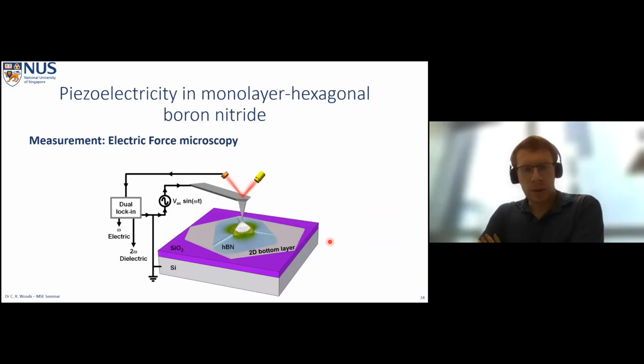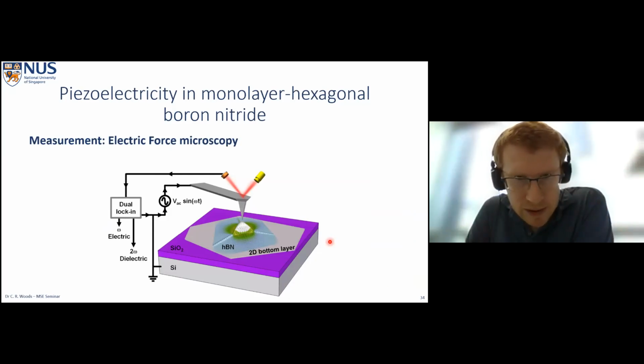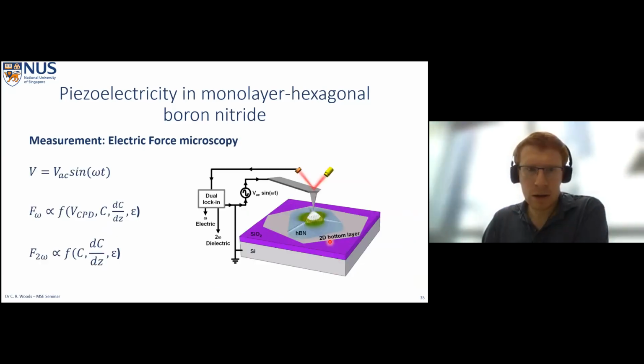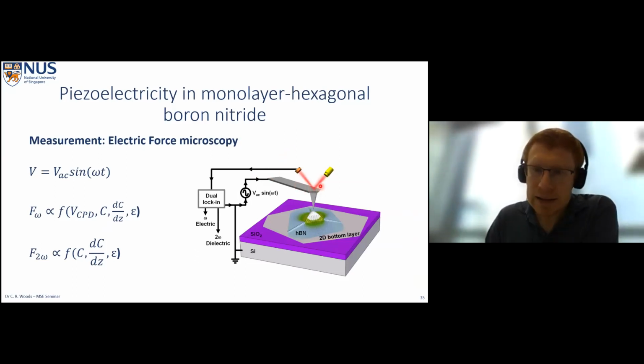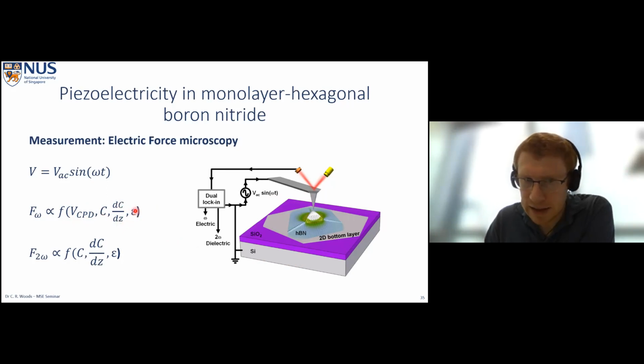So what we did next was we took our samples, monolayer boron nitride on graphene, and we did some electric force microscopy. When we do this, we can pass an AC voltage between our metallic tip and our silicon backgate. And if you have an AC voltage between the tip and the backgate, you'll get forces related to the contact potential difference between the tip and the backgate, the capacitance, how the capacitance changes in the Z direction, and the dielectric of the material in between.